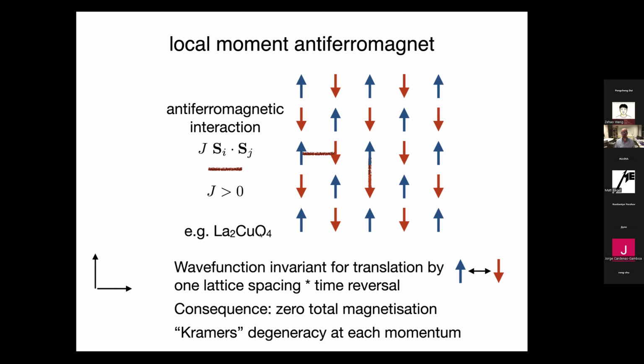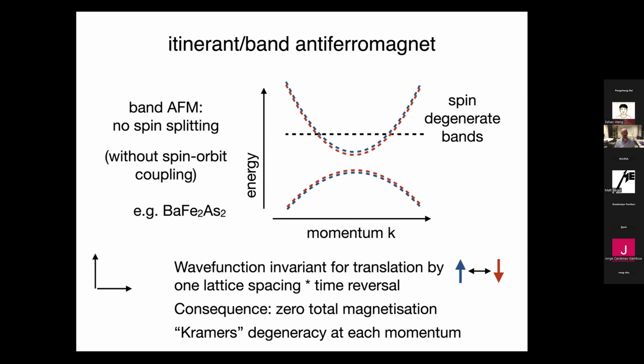In this case, the wave function is invariant for translation by one lattice spacing, but at the same time, I have to do a time reversal, or I have to flip the spins. And because of the time reversal or the spin flip that relates the two sublattices, the total magnetization of this antiferromagnet is 0. And as a consequence, there's a Kramers degeneracy at each momentum, as I will illustrate in this viewgraph.